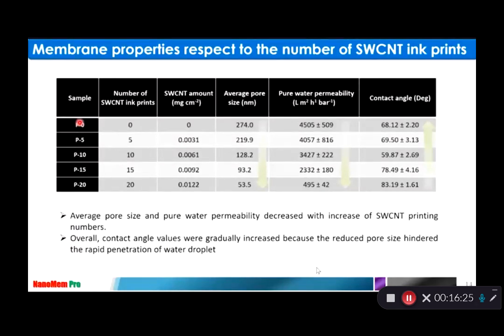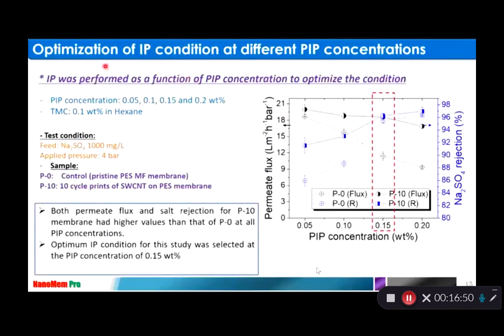When you have more cycles, the average pore size changed from 274 nanometer to 53, and the pure water permeability also changed from 4500 LMH per bar to 495, and the contact angle increased because of the carbon nanotube. So that's the overall membrane property.